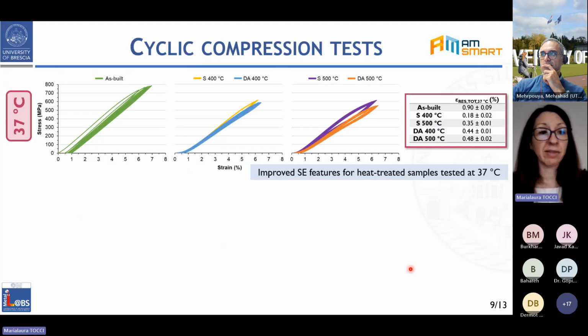Moving to the test carried out at 37 degrees Celsius, we can observe that we confirm basically what was already observed: improved superelastic behavior after heat treatment and slightly lower residual strain at the end of the experiment after the heat treatment.